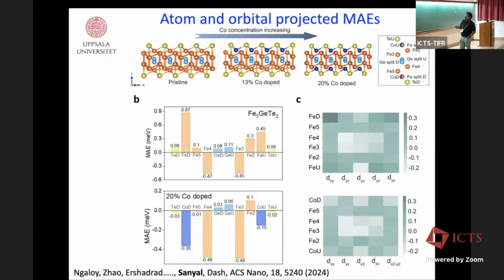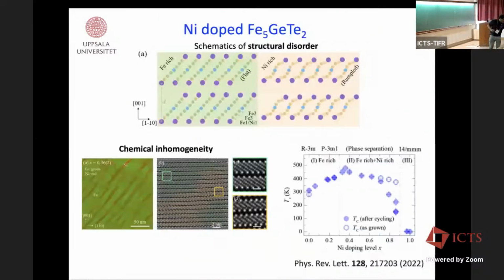Not only that, you see that these values are increased here, and then this is also replaced by the cobalt up atom. You see that instead of positive, it becomes negative. So from looking into these things, one can find out why, due to cobalt doping, the system wants to have an in-plane magnetization: because of this particular substitution of cobalt atoms. And then one can go into even more detail by looking into this heat map of the orbital composition, but I am not going into those details.